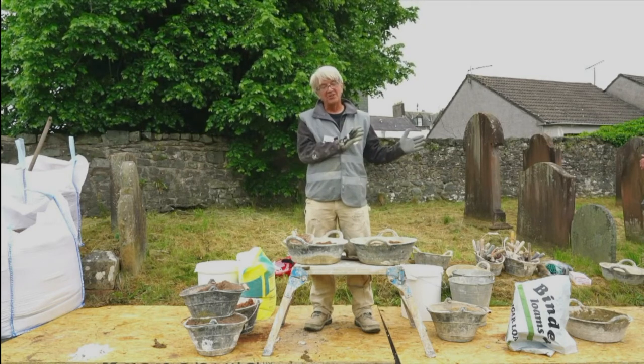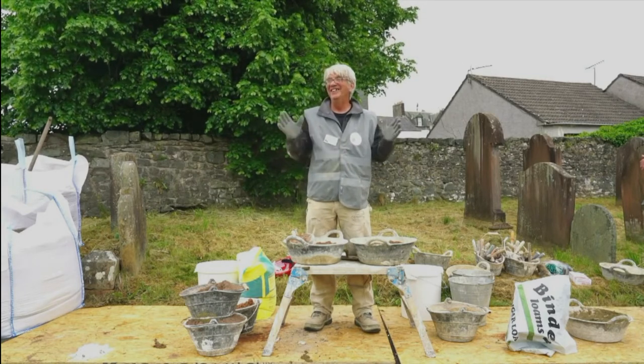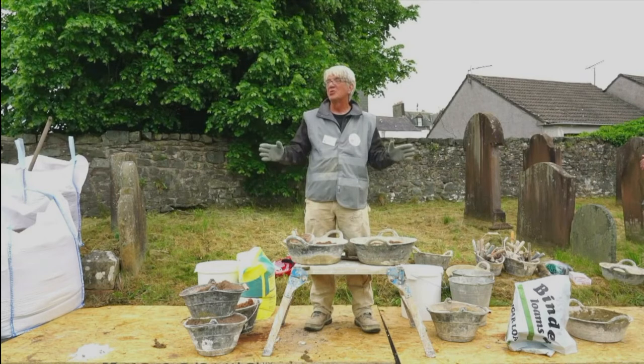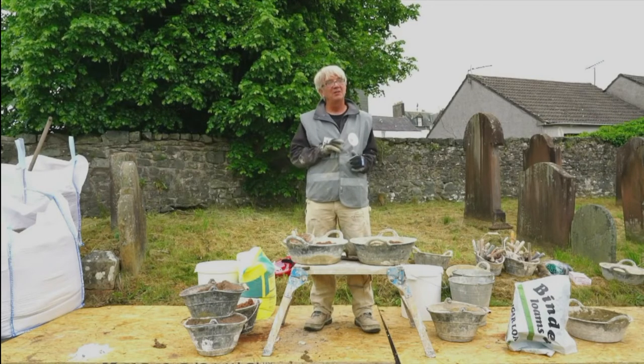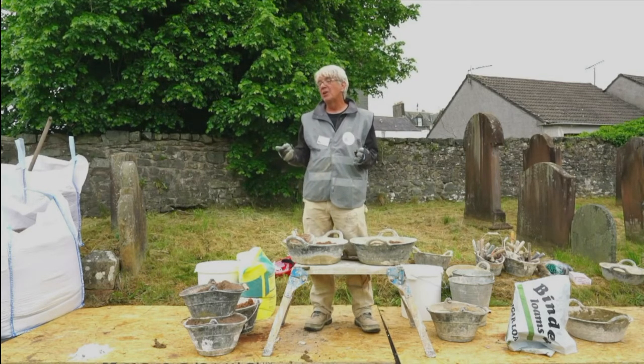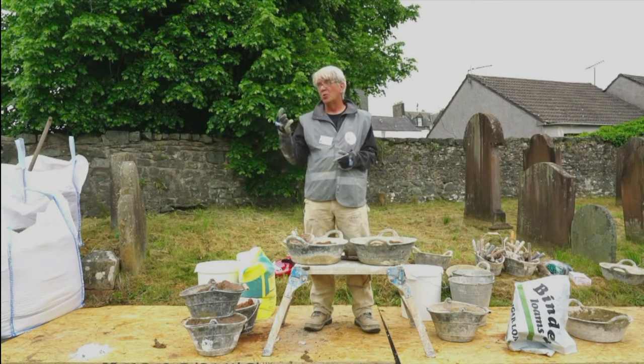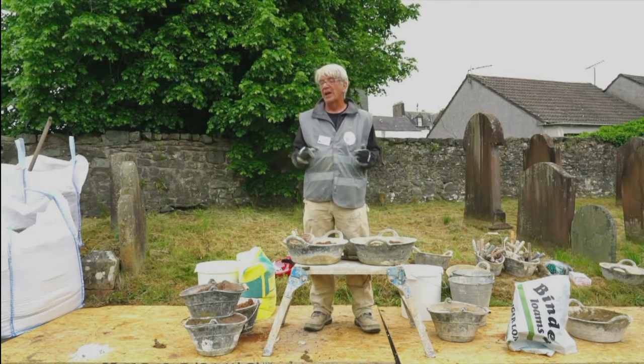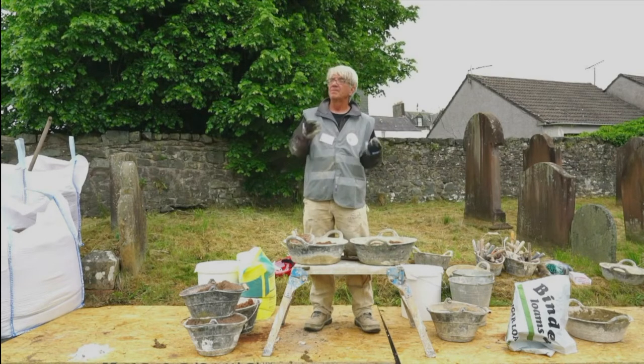As I say, historically they generally say just sufficient water to slake it, like we know what that is. It's only towards the end of the 19th century you get some engineers who put figures on this. So that's what I'm talking to you about. If you want to end up with a dry hydrate, there we've got one, we made one earlier, you add 1 volume of water. It needs back a third in weight of water, because that's generally what it's lost in the kiln. That's what it wants back. So, translated into volume, 1 weight is about 1 volume of water to 1 volume of quicklime.